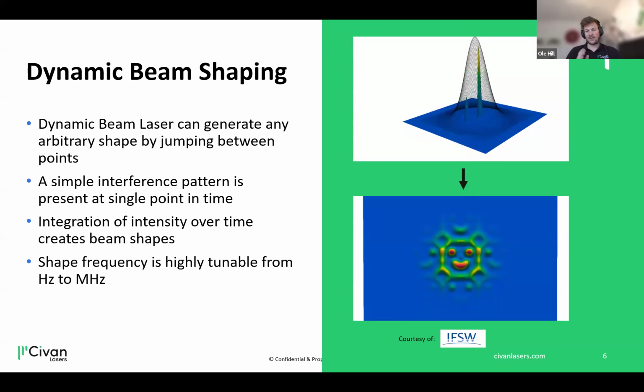But it's important to note that at a single time point, it is just an interference pattern. It's not the entire shape. But if you go to something like 100 to 500 kilohertz of refreshing rate, the material feels the laser radiation as if it were a static projection. And this is all to control the melt pool and tailor it to a specific application. Maybe you need more penetration depth in one part of your piece and less in a different part. Or in the die-cast application, for example, we want first a very deep penetration, and then for the second pass we just want heat conduction welding.